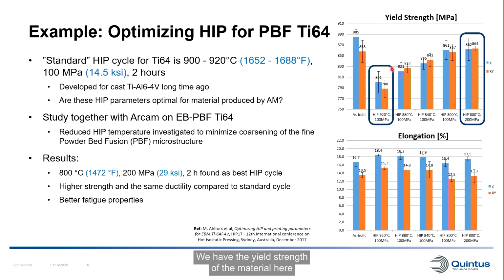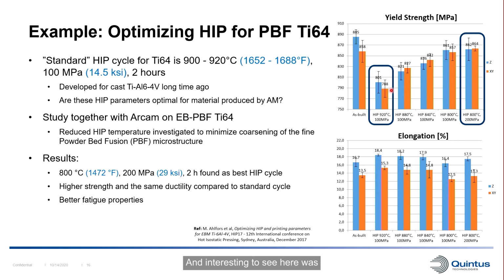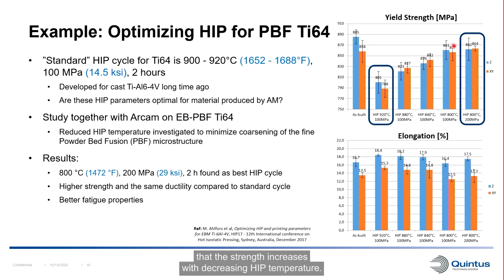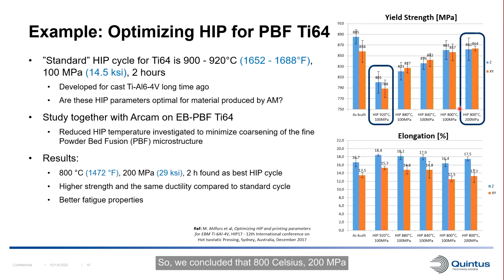We have the yield strength of the material here, and these bars show the yield strength of the material that's been treated with the standard HIP process at 920 degrees Celsius. Then when we go to the right, we see that we have decreasing HIP temperature: 880, 840, and even 800 Celsius. And interesting to see here was that the strength increases with decreasing HIP temperature. So we concluded that 800 Celsius, 200 megapascals, and 2 hours gave the highest strength.